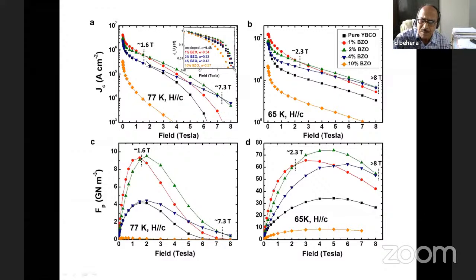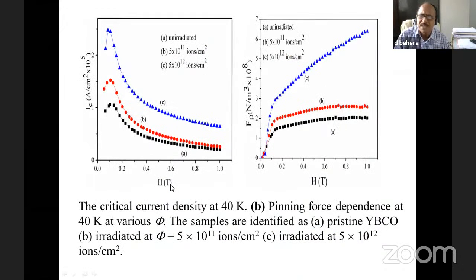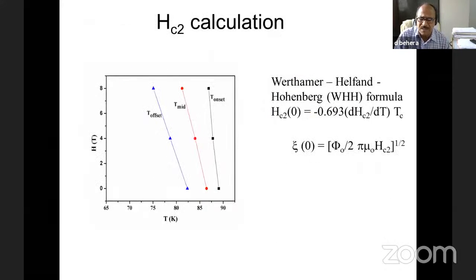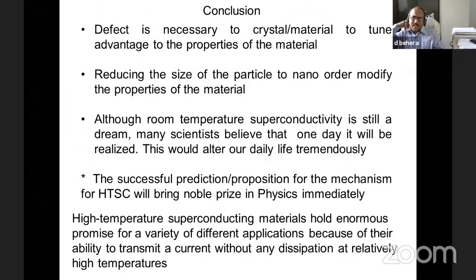The critical current density can be measured at different fields and different temperatures. Not only can we measure the critical current density, we can also measure the pinning force. Look at the pinning force: you enhance the pinning force in this material. The same holds for another material with different fluence and different energy, where we observe the critical current density. Also, we can measure the upper critical field Hc2, the highest field that your material can sustain, from the same experiment. So in conclusion, we can say that defects are necessary in a crystalline material or metal to tune